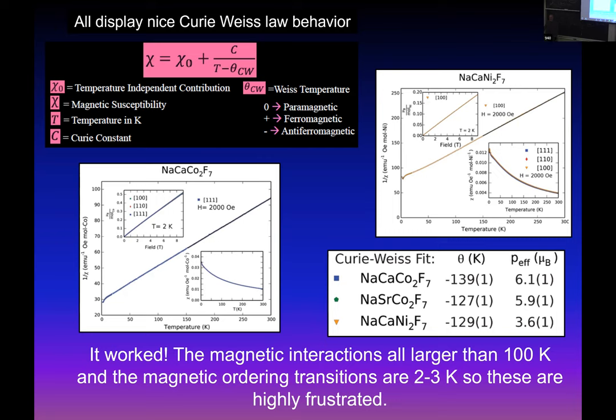And so the way this works is that the slope of this line in 1 over chi versus T tells you what the magnetic moment is, and the intercept of that line tells you what the strength of the magnetic interactions are. You can see the intercept of that line is like 129 degrees negative, so the spins are very strongly interacting, and they're not magnetically ordering down to low temperature. So nothing happens in this until 1/50th of the expected ordering temperature. So the spins are really, really frustrated in this fluoride pyrochlore.